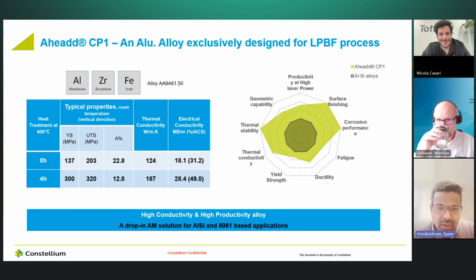Again, thank you, Matthias, for giving the short introduction about the project topic. And before we get into the details of the design and the component level testing, I would like to give you all a small insight into the material properties and what you can expect from this material. So Aheadd CP1, C stands for high conductivity and P stands for high productivity. This is an alloy that we have exclusively designed for the laser powder bed fusion process. And it's an alloy of 98% pure aluminum and 1.1% zirconium and iron.